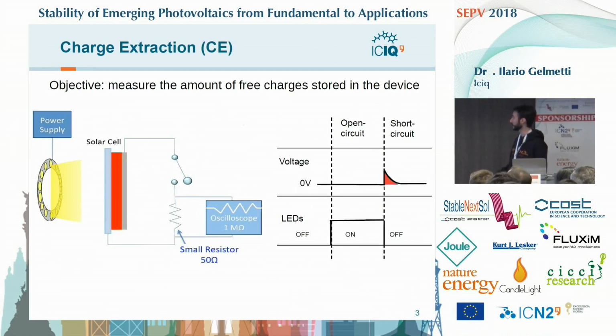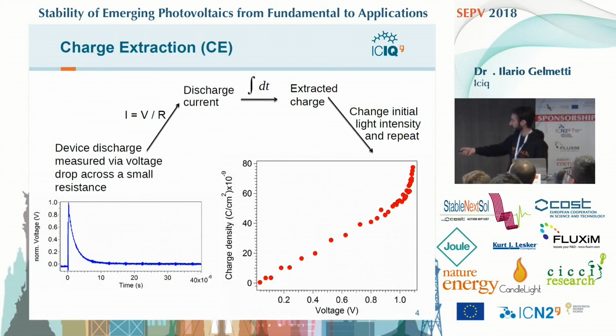transients. For example, one of the first techniques that we use is the charge extraction, which basically is we take a full device, we illuminate in open circuit condition, then suddenly at the same time we short circuit it and we switch off the light. So we try to extract as fast as possible all the charges contained in the device. So we obtain a voltage decay, measuring with an oscilloscope through a small resistor. We can convert the voltage profile to a current profile knowing the small resistor, we integrate in the time, so we obtain the area, so the charge that was extracted.